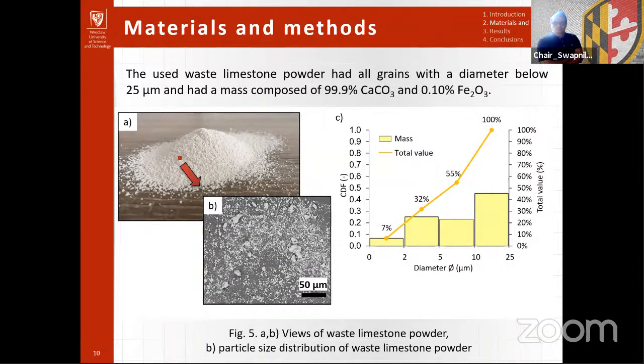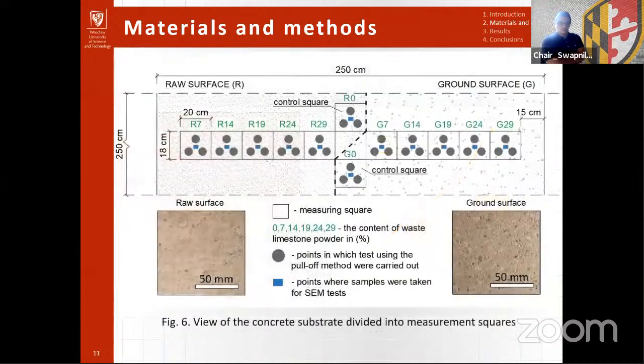entirely of calcium carbonate. In our research, we prepared a concrete substrate and divided it into 2 areas with different methods of substrate surface treatment. We ground half of the surface of the substrate mechanically to obtain a ground surface. The other half of the surface was a raw surface. We separated squares of both types of surface.